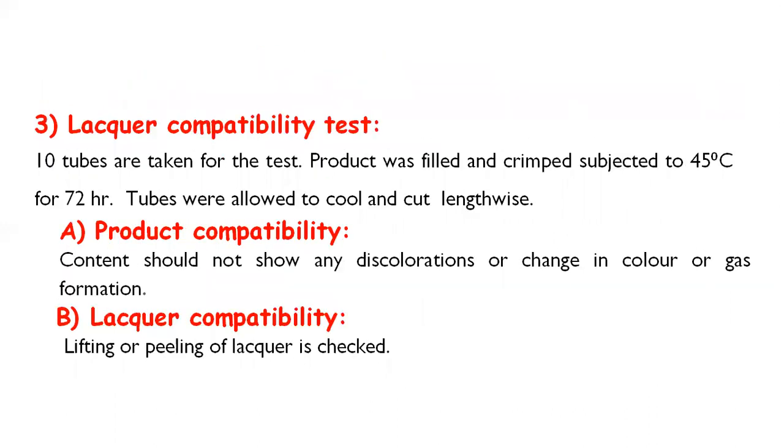Lacquer compatibility test. 10 tubes are taken for the test. Product was filled and crimped, subjected to 45 degrees Celsius for 72 hours. Tubes were allowed to cool and cut lengthwise. Product compatibility: content should not show any discolorations or change in color or gas formation. Lacquer compatibility: lifting or peeling of lacquer is checked.